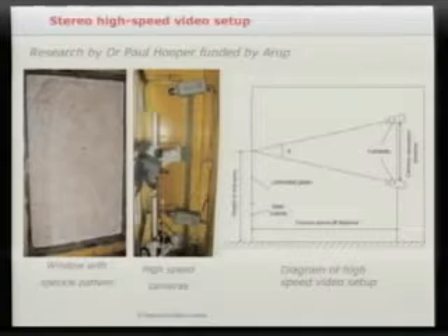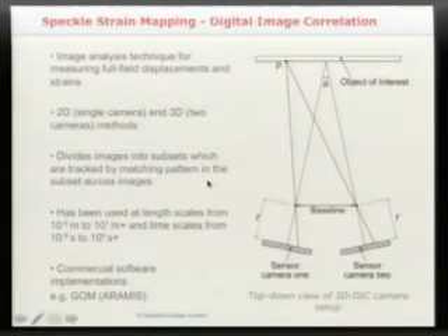And the principle of this is that you have two cameras with a well-defined triangulation angle, and you can use calibration plates to effectively tell the cameras where that speckle pattern is and how it moves. And then the high-speed cameras track the movement of those speckle features. And you can do this for very small structures and large structures and over different time scales as well. And this is using the software which we're going to show you in a moment.